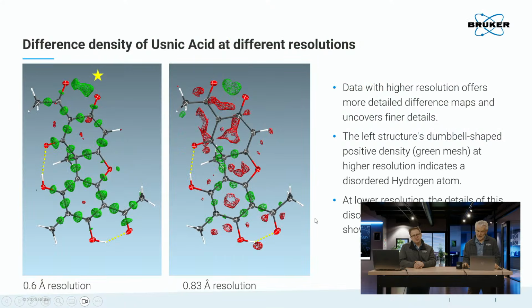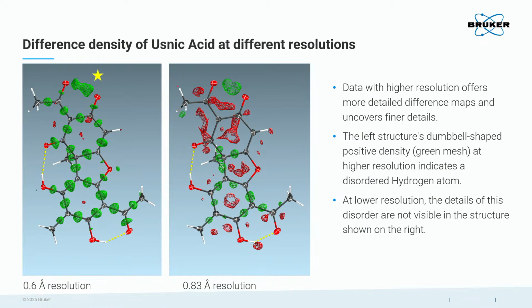Also, if you look at organic molecules, you could argue, oh, it's fine to get a picture at like 0.83 with copper. Well, why do I need higher resolution? And you just get more detail. So here's an example of keto-enol tautomerism. Just like here, where you have a very well defined hydrogen that's hydrogen bonded between these two oxygens. In this case, it's actually disordered. And only when you go to a higher resolution, a better d-spacing of 0.6 angstroms, you can see that. At 0.8, it's just a blob.